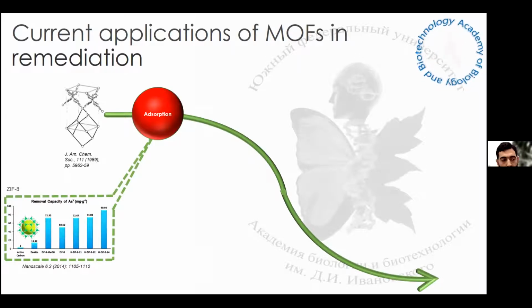The first example is adsorption, where metal-organic framework offered selectivity to the adsorption process. Because we cannot have an unselective reaction. Now in 2021, we should forget about unselective adsorption. We should target exactly each pollutant and remove it from the solution. And from the research papers that I see, metal-organic framework offered a high adsorption capacity for different radionuclide materials. Here is an example: you can see that the researchers used ZIF-8, and you can compare the adsorption capacity with normal activated carbon or zeolite. The adsorption capacity is almost 8 times higher. So it justifies the use of this nanomaterial for the removal of arsenate from the solution.